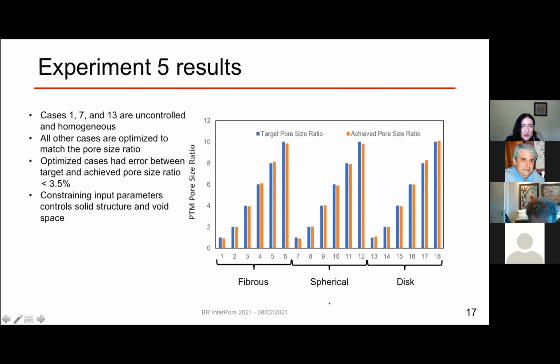And we have the experimental results here showing cases for fibrous, spherical, and disc-shaped inclusions. On the vertical axis is the pore size ratio. Blue is the target that we want to achieve, and orange is the achieved pore size. And these are our sample numbers. So 1, 7, and 13 are homogeneous, so there was no gradient. And you see that we can hit the pore size very well, no matter what is the type of the inclusion and what is the pore size ratio.